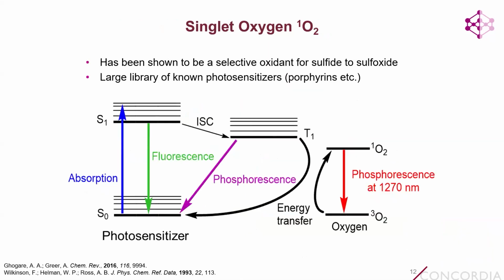And so there are different ways that you can selectively oxidize sulfides to sulfoxides. And one way to do that, that's been shown in the literature a lot in the past, is to use singlet oxygen. And there are also different ways that you can generate singlet oxygen, but one way to do that is to use a photosensitizer. So something like a porphyrin-based compound or a pyrene-based compound. And so just very briefly how this works, our photosensitizer absorbs light, you generate the singlet state of that photosensitizer. If you have efficient intersystem crossing, which can be aided by a heavy metal like the rare earth elements that we use, you can generate the triplet state of that photosensitizer.